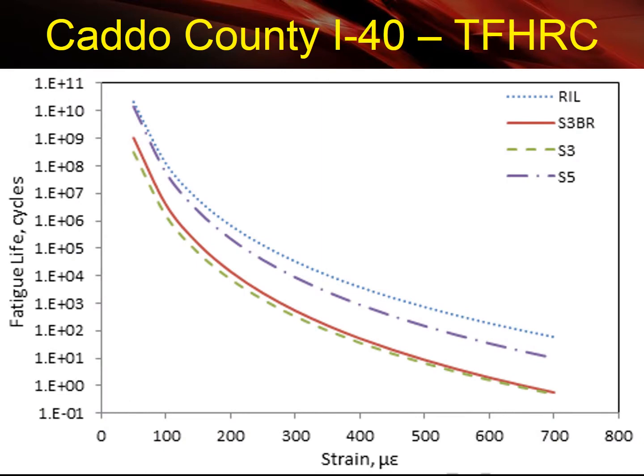And while we were doing this test, we got those mixtures. We sent them to Nelson Gibson at the Turner-Fairbank Highway Research Center. And I'd presented this data to you before, but this is the one plot that I like showing. There's that rich intermediate layer. In fatigue resistance, that's a lot better than the others, right? And then here is this S5, which is the surface mix. So this is the fourth mix down. This is the top lift, essentially. And then this S3 is that 19 millimeters. This has a recycle in it. We use this on the shoulder, so we're going to go ahead and test it. Surprisingly, it did a little bit better than the S3 without any recycle in it. I'm not sure why that was, but that's the way it turned out.